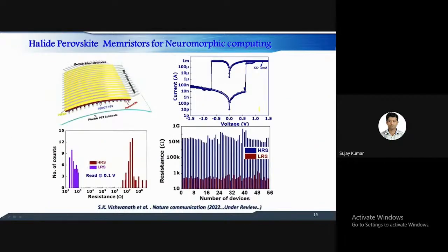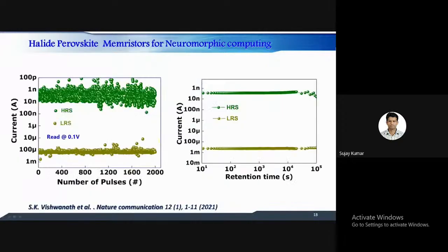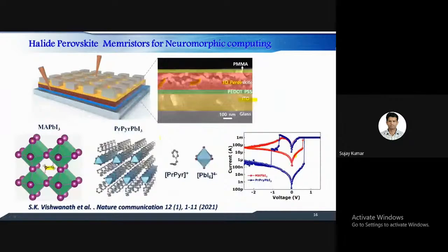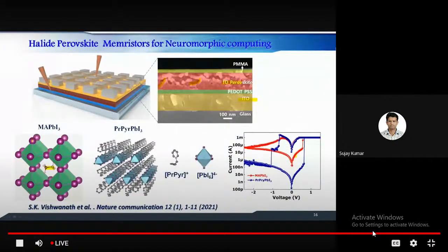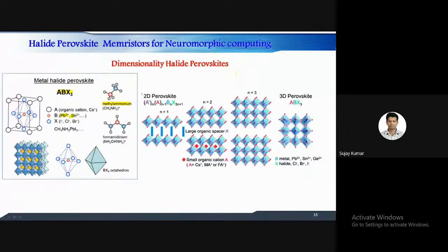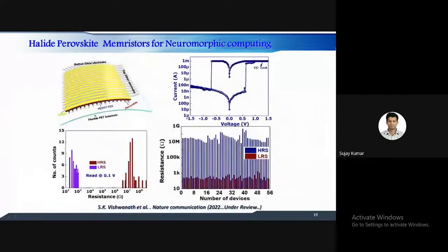We also extended this work with a crossbar memristor, which is generally used in practical applications. Here we use bottom and top silver electrodes with the same memory architecture. Instead of ITO, we used silver, and on the top also silver. So we made a crossbar memristor with top silver and bottom silver, and the remaining structure is the same.